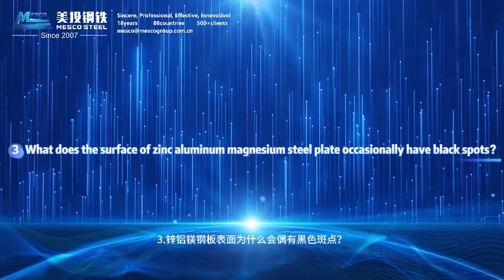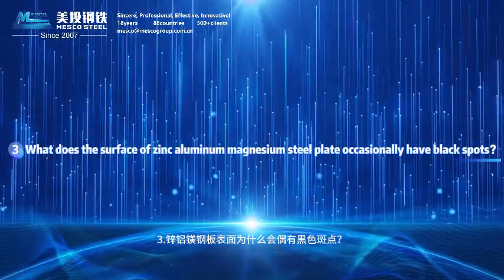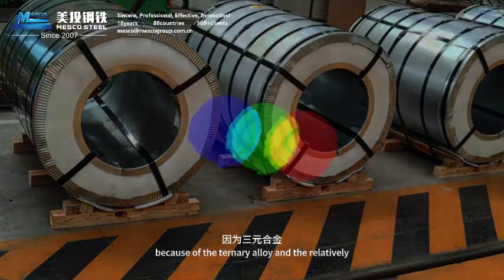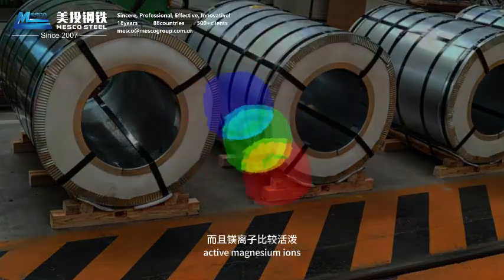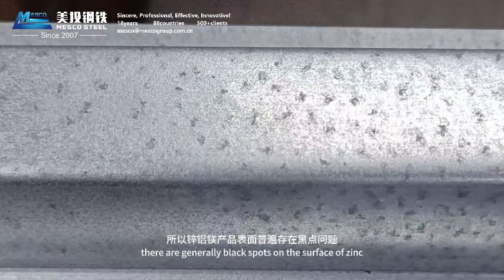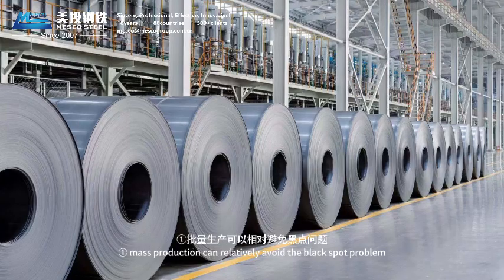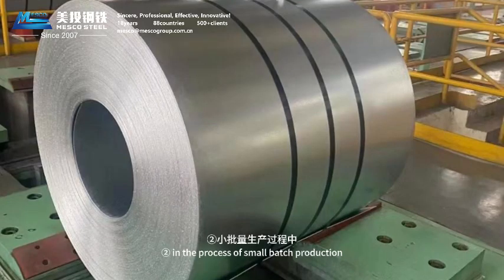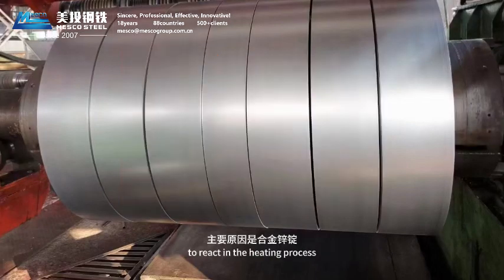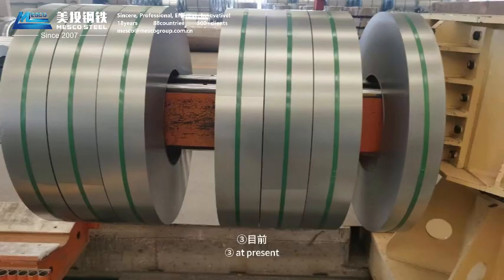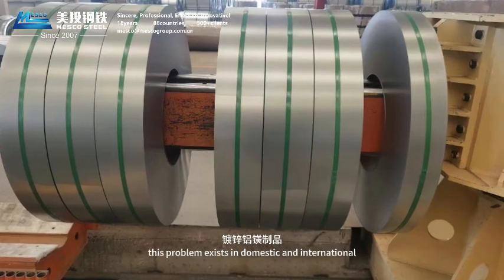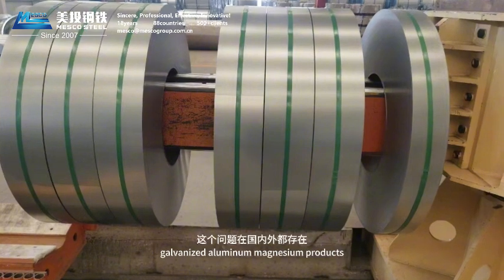Why does the surface of zinc aluminum magnesium steel plate occasionally have black spots? Because of the ternary alloy and the relatively active magnesium ions, there are generally black spots on the surface of zinc aluminum magnesium products, which are objective and unpredictable. First, mass production can relatively avoid the black spot problem. Second, in the process of small batch production, it will be relatively obvious. The main reason is that the alloy zinc ingot fails to get sufficient time to react in the heating process. At present, this problem exists in domestic and international galvanized aluminum magnesium products.